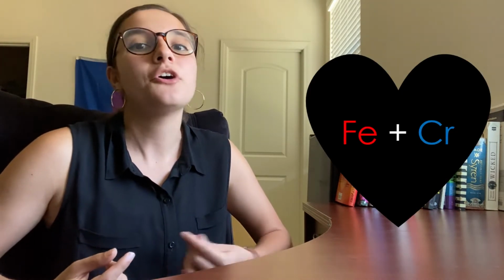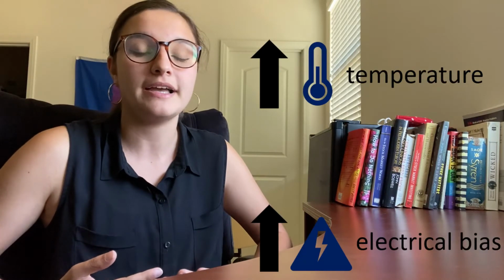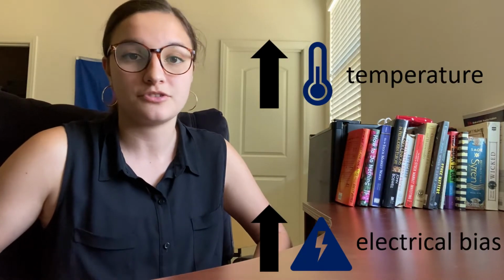In many cases, we want a single crystal film to study. Pure iron thin films have been produced with close to ideal structure, but adding chromium complicates that landscape. Because of the attractive forces between iron and chromium, the chromium atoms will stall the diffusion of the iron atoms, creating heterogeneous growth. Because of this, the experiments have required a higher applied temperature and applied electrical bias in order to get closer to the ideal structure.